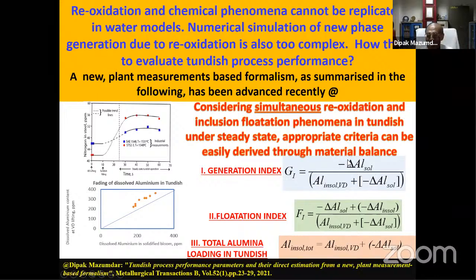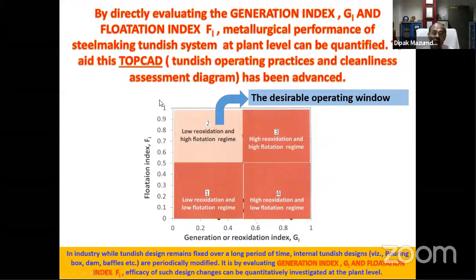And this is not just for aluminum. You can do it for magnesium, for calcium treated steel, for silicon, for anything which fades in the Tundish. You should be able to derive a similar kind of criteria. So by evaluating this flotation and generation index, you will be able to find that out. And now you can construct parameters that vary from 0 to 1, as I have indicated.